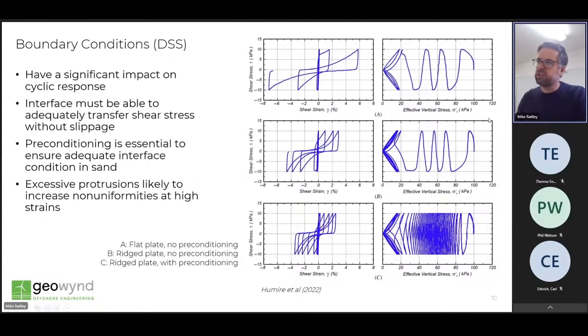Now, cyclic preconditioning is an important phase of the test whereby a number of cycles are applied to the specimen under a constant normal stress condition prior to constant volume cyclic loading being applied. This allows some bedding of the interface and also some pre-shear of the sample to allow it to better accommodate cyclic loading, as you would see in situ under small load action from foundation interaction.